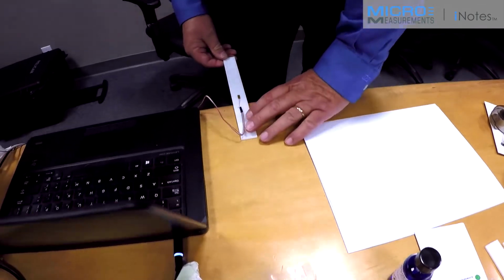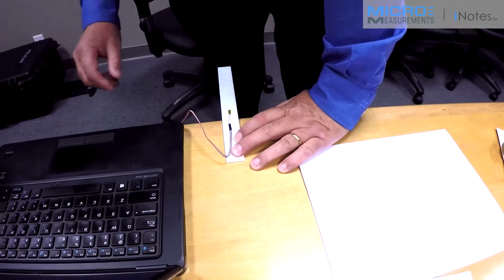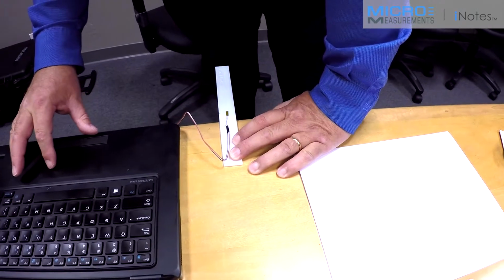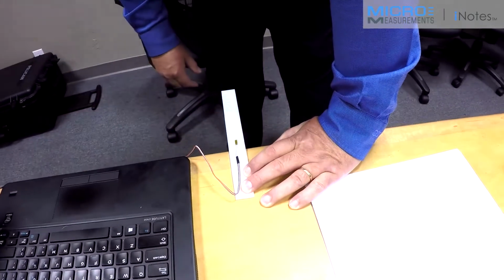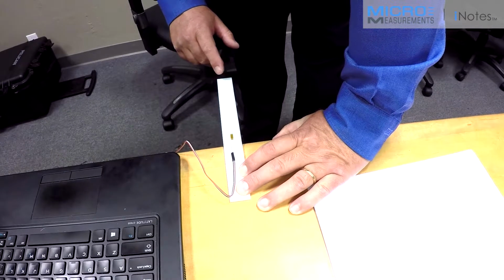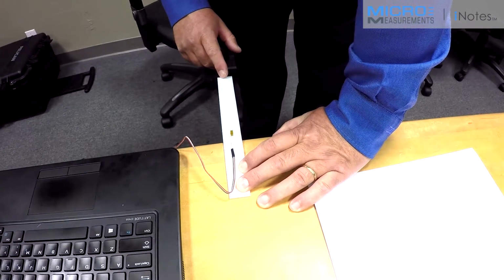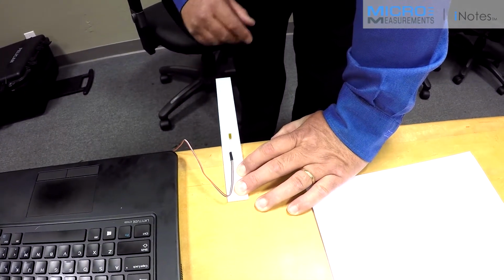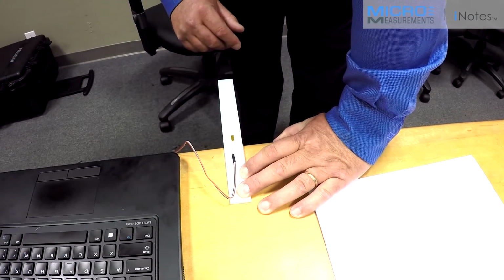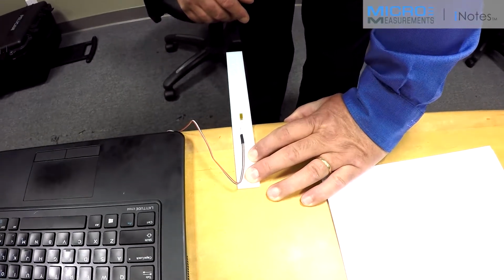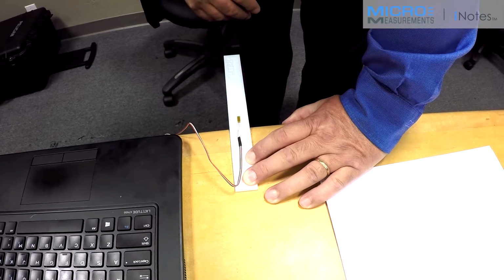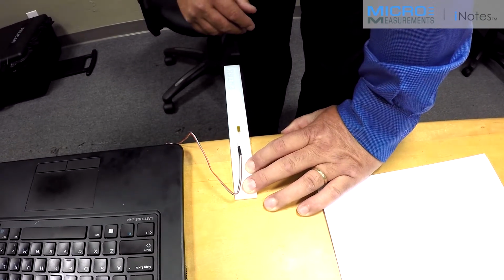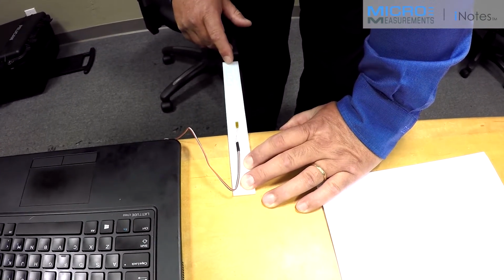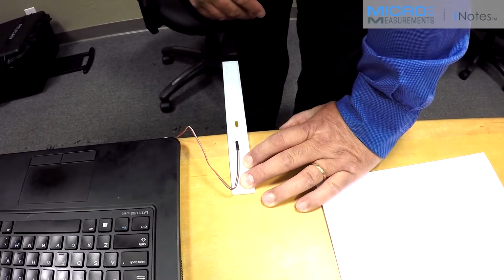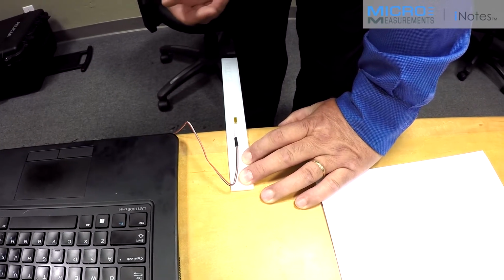And you can see that initial zero output on the display of the P3. And so we'll position the beam so that the gauge is just off the edge of the table in a cantilevered fashion. We'll zero balance the initial zero offset and look at zero stability. Then I'm going to apply some load, remove that load, and look at the zero return. If the gauge does not come right back to zero, that's indicative of plastic creep in the 3D printed plastic.